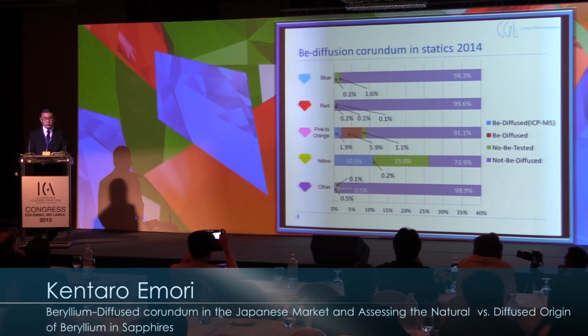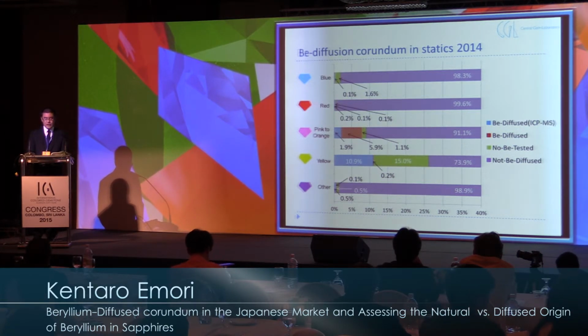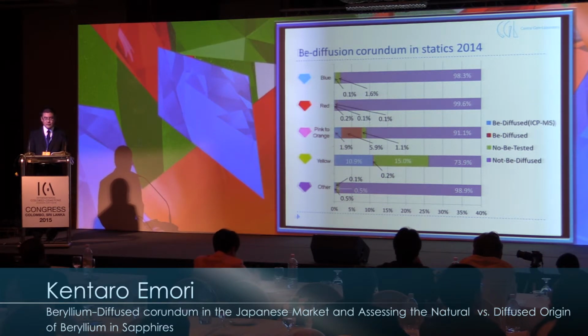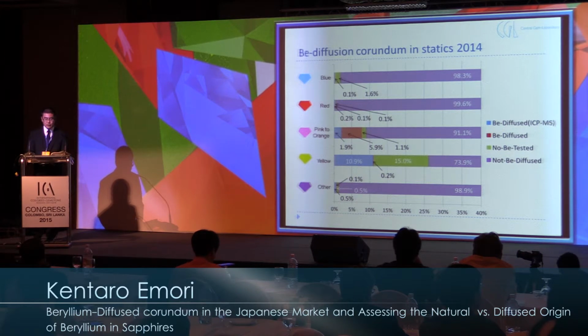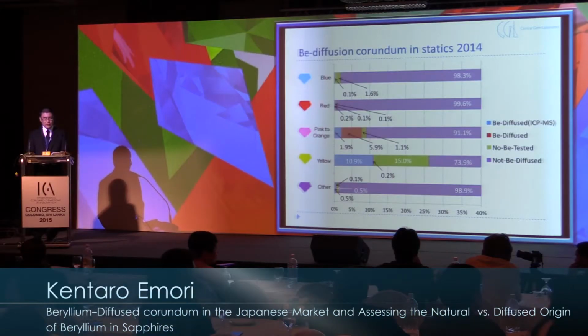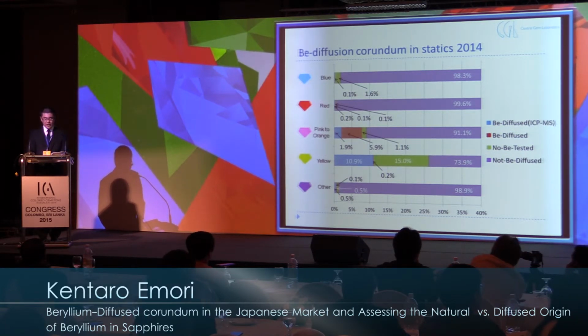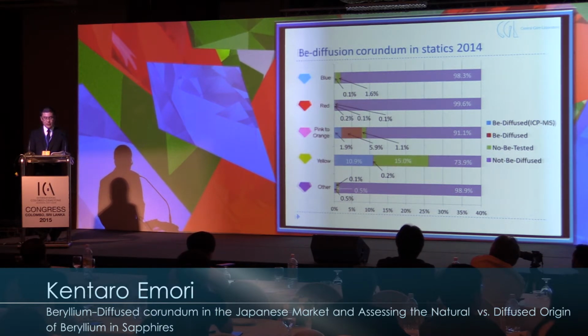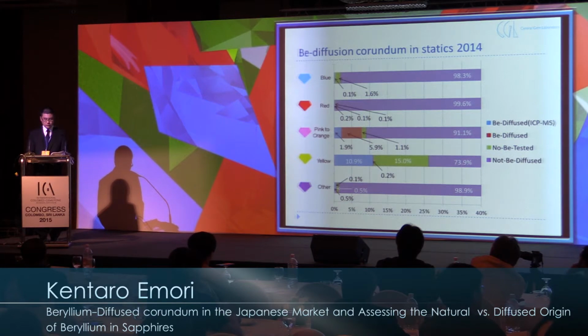This slide shows the proportion of beryllium-diffused corundum for each color. To make it easy to look at, this graph is cut at 40% on the right side. The corundum samples are classified into 4 groups. Beryllium-diffused corundum determined by LA-ICP-MS is shown in blue. Beryllium-diffused as determined by standard identification methods such as a surface conformal layer is shown in red. Green shows corundum which were not analyzed by LA-ICP-MS, although we suggested customers inspect the stones by LA-ICP-MS. Purple shows stones identified as not having suffered beryllium diffusion treatment by routine techniques.